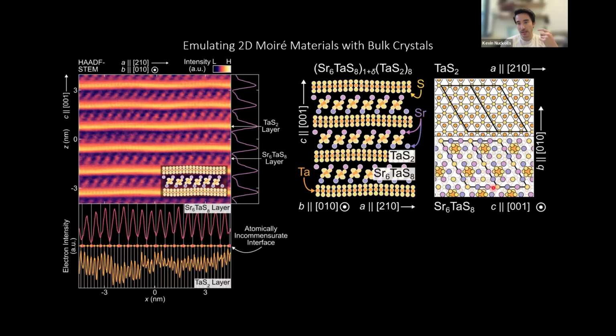And the parallelogram here is the spacer layer's unit cell. So here is where we can see half incommensurate, half commensurate lattice structure. So you can see that this unit cell, this top edge, is commensurate with this spacer layer, and it's commensurate with this tantalum disulfide layer. And so this is the commensurate direction, the vertical b-axis. Whereas the orthogonal direction, you can see that the parallelogram is commensurate in the spacer layer, but it's incommensurate with the tantalum disulfide layer. So this is the atomically enforced incommensurate direction of the lattice. And so putting this all together, this aperiodic composite crystal manifests our design principle because they have similar symmetry, similar lattice constants, and so they produce a Moiré modulation in a bulk crystal.